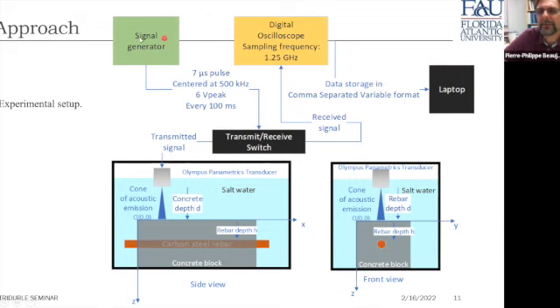Now, in terms of signal generation, the signal generator produces a 7 microsecond pulse at 500 kilohertz, 10 times a second. The signal is transmitted, and then this transducer is a reciprocal transducer. The sound is going to travel through the cone to the concrete. Some of it is going to penetrate in the concrete, reach the rebar. Some of it is going to be reflected off the rebar, travel back through the water, and reach the transducer again. So we're going to have a series of echoes, a surface echo from the concrete, an echo from the rebar. And then after that, we will have multiple bounces that are going to add to the signal generation.